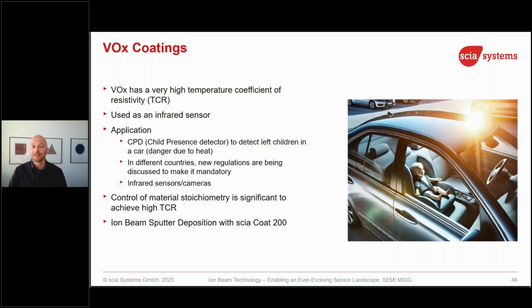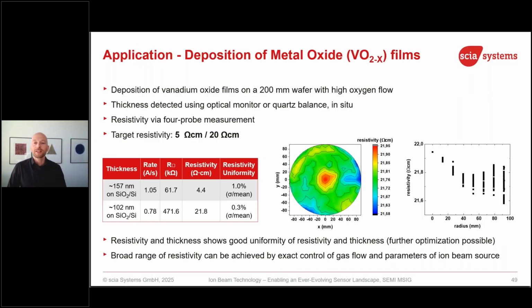And basically you need a sensor material which has a very high temperature coefficient of resistivity. Means if the temperature of the sensor material is changing, you get a high resistivity change. So that's the sensor principle. And vanadium oxide is one of those candidates, but actually it's just in a certain phase. It's not like for VO2 or some other phase where you get these high properties. You need to have the right mixture, maybe adding also some other dopings. And we are able to control this very precisely with our scia Coat 200 system.